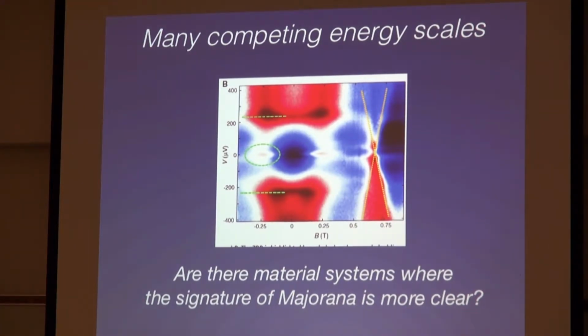And I think since then, as people often do with very good, interesting experimental work, they start to pick it apart. I'm not going to make a stand about whether this is or isn't Majorana, but there are some interesting things people have noticed about this data that point to it maybe not being Majorana. So this is now a two-dimensional plot of the bias and the magnetic field. This is all these slices from the last graph laid on top of each other, and out of the board is conductance. If you look at B equals 0, you don't see a peak in conductance. But then as you apply a magnetic field, you start to see a peak.